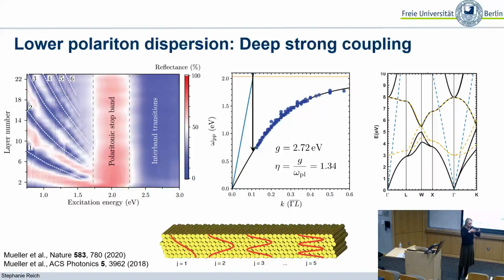But for that we need to cut the crystals. And we have started discussing with people who do focused ion beam milling. Is that the calculation result, you don't have the experimental? No, we don't have the experiments yet because you need to cut a lamella out of this crystal and then put it down and do the measurement. So it's not extremely straightforward. Could you self-assemble in different ways to control the orientation of the growth? If we use these large monodisperse gold nanoparticles, they always grow along the 1-1-1 direction of FCC.